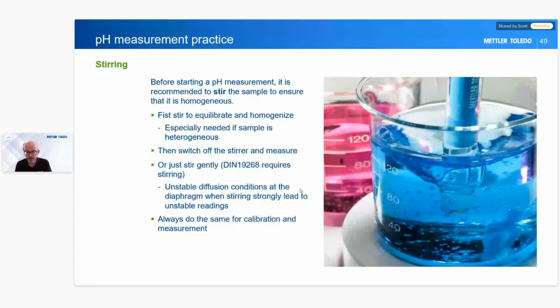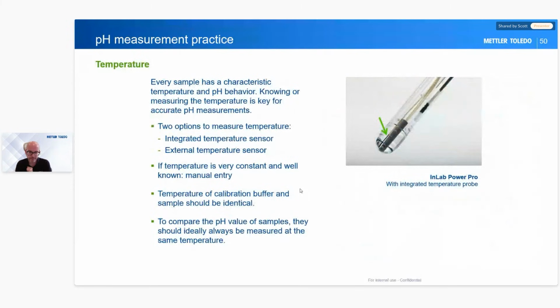Now, when we're taking measurements, we generally don't want to stir, because when we stir, we introduce air into our sample, and that air can introduce other things like carbon dioxide from the air, for example. So we need to switch off and then take a measurement. Some methods, the DIN method, for example, requires stirring. So if we are going to do that, we need to make sure the stirring is at a low volume. It's not mixing or swirling the sample, yet again, to stop that air.